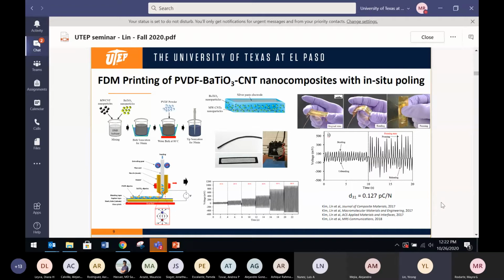We have barium titanate nanoparticles inside of a DMF solution. At the same time, this DMF will have PVDF powder, which is also piezoelectric. And then you can make a composite that has these barium titanate nanoparticles together with the PVDF. So we can make a filament, as you see over here in the middle. It's a black filament that has carbon nanotubes, barium titanate, and also PVDF in it. We're making this filament ourselves, then we loaded it into the most commonly seen 3D printer, an FDM tabletop, right? So you can print it, and at the same time, you add a high voltage between the nozzle and the substrate, so you can align these dipoles.